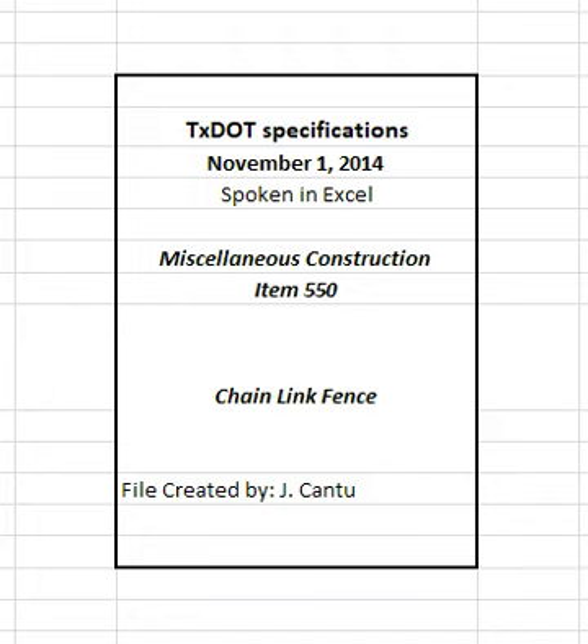2.15.4 Tension wire. Zinc coat tension wire with a minimum coating of 0.80 ounce/square feet or aluminum coat with a minimum coating of 0.30 ounce/square feet. 2.15.5 Barbed wire. Zinc coat barbed wire in accordance with ASTM A121, 0.80 ounce/square feet, or aluminum coat in accordance with ASTM A585, 0.30 ounce/square feet. 2.15.6 Pole cable. Zinc coat pole cable with a minimum coating of 0.80 ounce/square feet of individual wire surface when tested in conformance with ASTM A116.